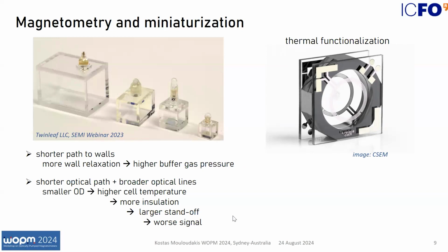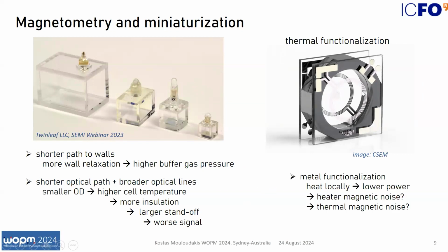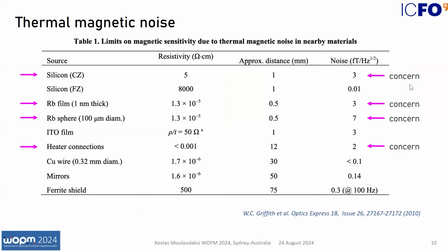To address these issues, we use thermal functionalization. We use integrated platinum heaters on the vapor cell, metal functionalization. In this way, we can heat locally the atoms with lower power, but this brings on the table new challenges, like, for example, what is the magnetic noise produced by the heaters and the thermal magnetic noise from these current traces. And to quantify these noises, we refer to this table by NIST, published in 2010, where they describe the limits on magnetic sensitivity due to thermal magnetic noise in nearby materials.